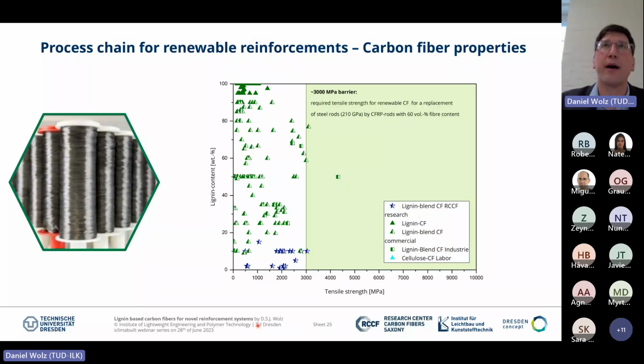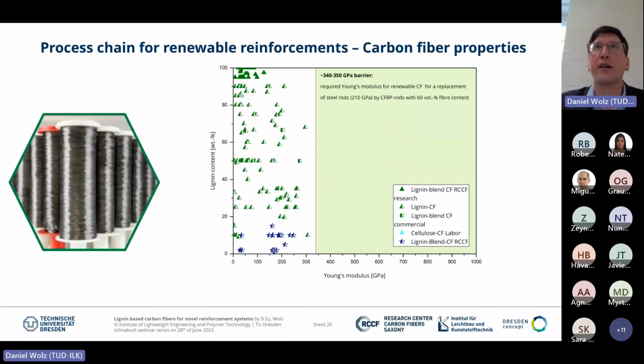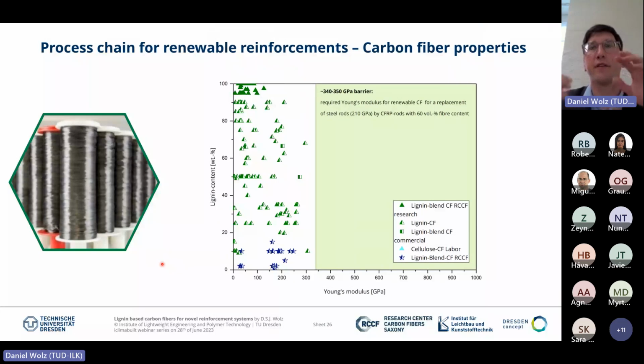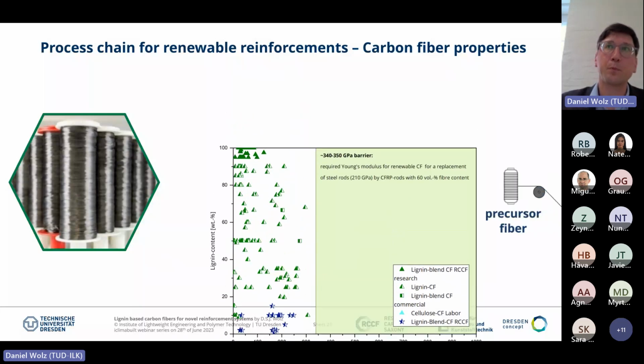Still, in the upper range, about 90%, 95% to 100% lignin, there is not a solution visible right now. Still, we have some solutions here which we could apply. But if you're targeting Young's modulus, there this barrier is not solved right now. So what we have to do in carbon fiber conversion is to bring new solutions to challenge this barrier, to apply and support the construction industry with new fiber solutions for these renewable carbon fiber reinforcement rods.